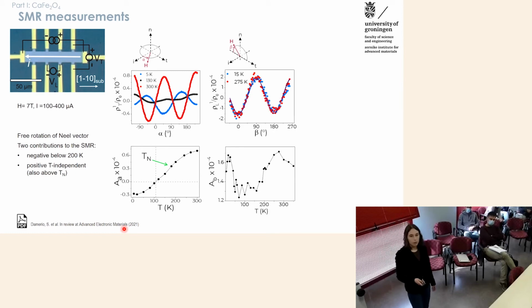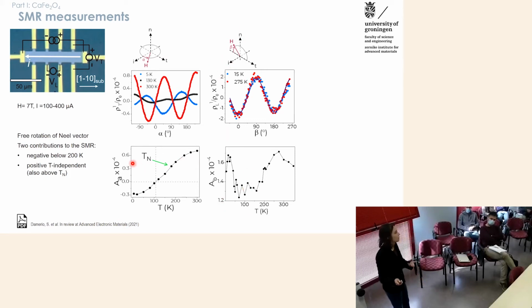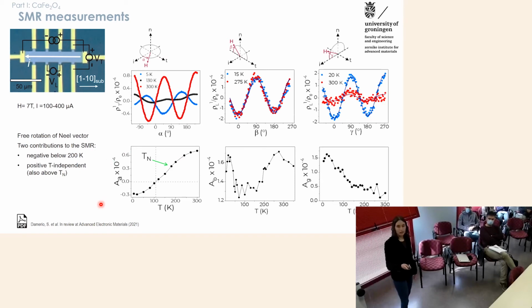And what was perhaps even more surprising is that we also saw a modulation when measuring in the beta plane, which is where we expect the modulation for a ferromagnetic material, where the magnetization follows the field. And we also saw a modulation in the other plane, where for a normal ferromagnet it was not expected. And this modulation decreases in amplitude with temperature. So what we are seeing here is that there are actually two components to this in-plane SMR signal. One is a positive component, more ferromagnetic-like, and one is the antiferromagnetic component from the longer range ordering.